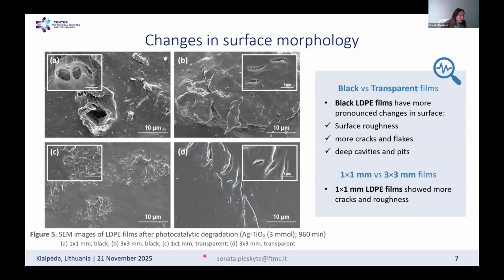Also, I want to dig a little more into the surface morphology and the surface changes that we observed. The most pronounced surface morphology changes were found in the black films with a size of 1 by 1 millimeter, which is represented in Figure 5, part A. Here you can see the formation of some cavities, like over here, and also more flakes and cracks. And probably the most interesting and important part is that we can also see the formation of deep pits. This kind of surface morphology change indicates the decomposition of the LDPE matrix, which most likely occurs due to the volatilization of organic materials and also main chain scission.